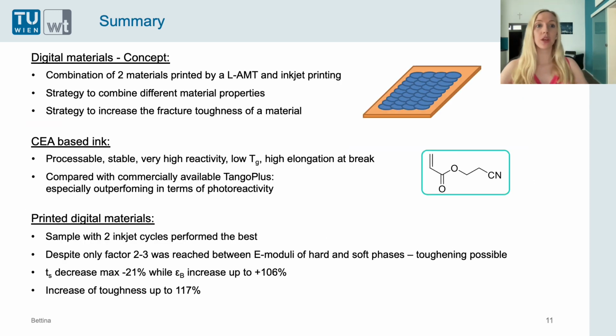So in summary, I want to say that we use the concept of digital materials to combine two materials by lithography-based additive manufacturing technology and inkjet printing. And we do that because we want to combine different material properties, and it's a strategy to increase the fracture toughness of a material. I developed the cyanoethyl acrylate-based ink, which is processable, stable, has a high photoreactivity, a low glass transition temperature, and a high elongation at break. And compared with the commercially available Tango Plus, it's quite similar in most properties, but it's really outperforming it in terms of photoreactivity, which is important for our application.